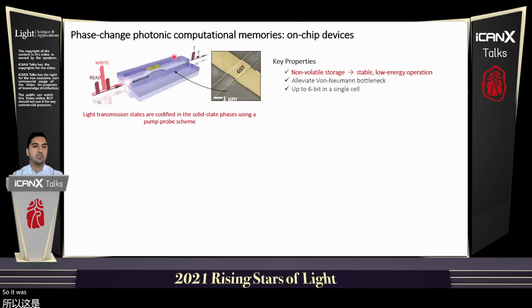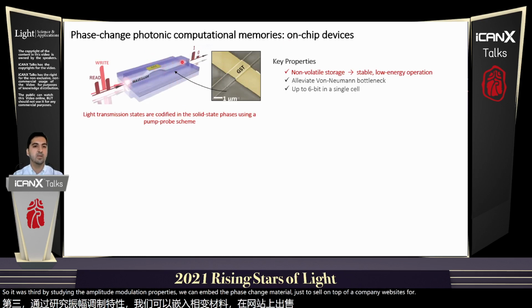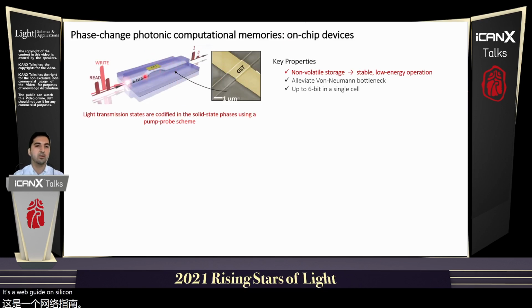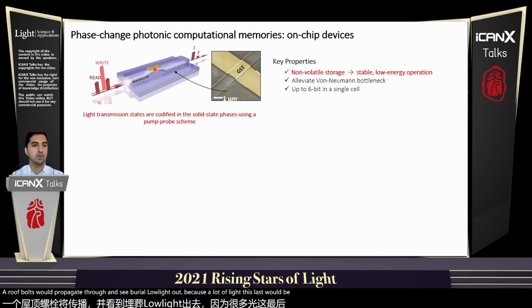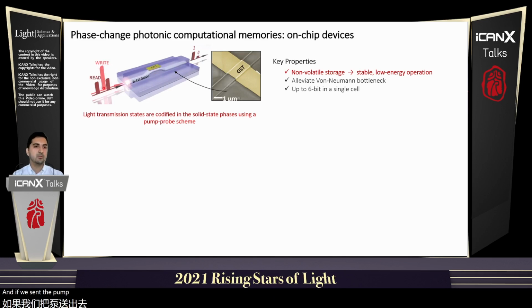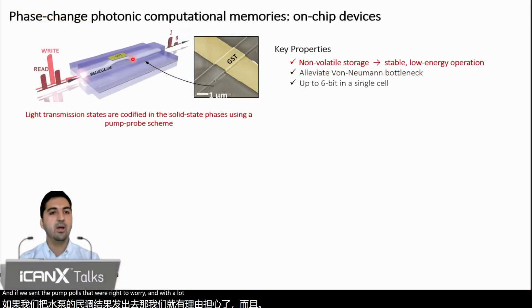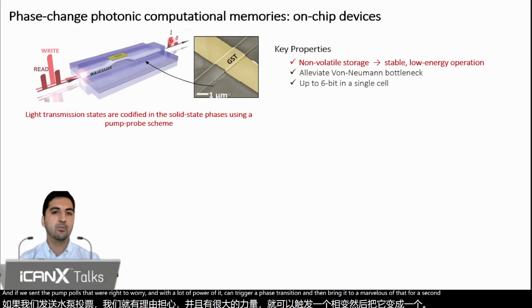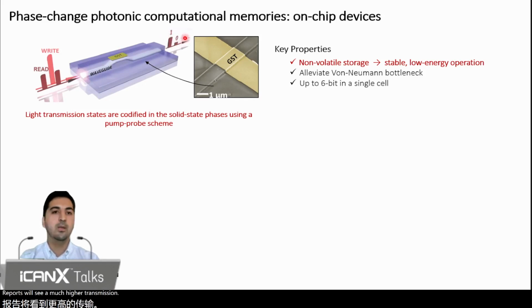So if we start by studying the amplitude modulation properties, we can embed the phase change material, a GST cell, on top of a photonic waveguide. So this is a waveguide on silicon or silicon nitride. And if it's originally in crystalline state, a read pulse will propagate through and see very low light out because a lot of light is lost to the material. And if we send a pump pulse that will write with a lot of power, it can trigger a phase transition and bring it to amorphous. So therefore, a second read pulse will see a much higher transmission. And we can therefore codify the information in the amplitude.